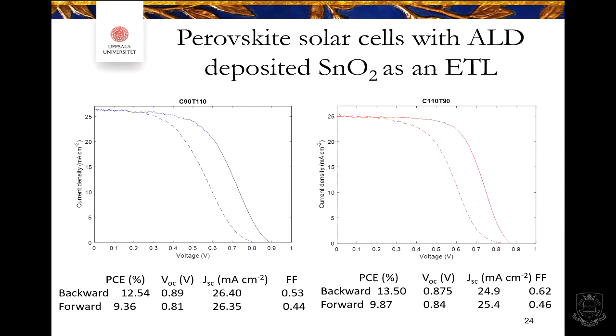And we have hysteresis. What hysteresis is like is if you are ramping the voltage in one direction, you measure your curve, and then you go from a high voltage and go back, and you plot those curves and look at that. So it's actually just how you drive the voltage. If you go from a high voltage value to low, or from a low voltage to a high voltage, you see differences in these two curves. So there is still possibility to develop the material.